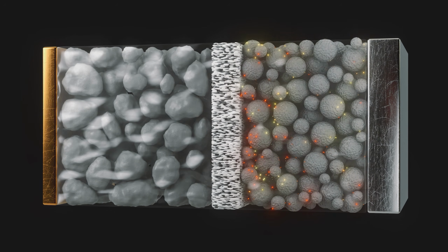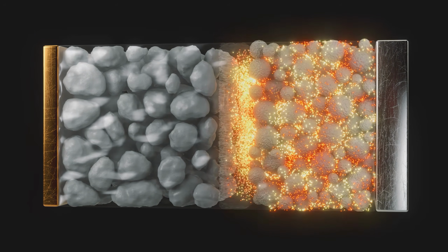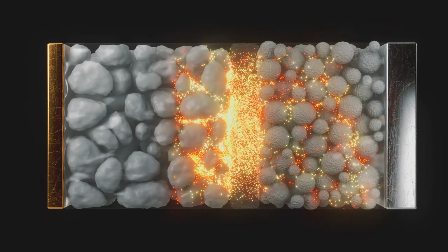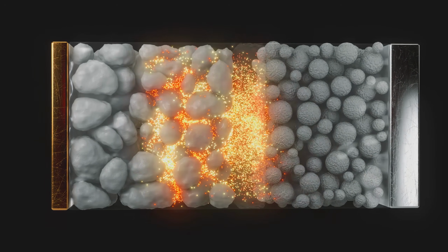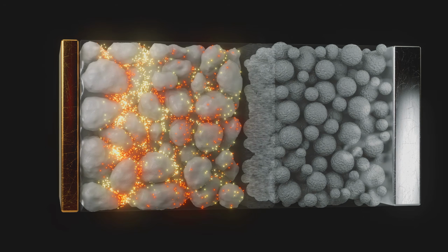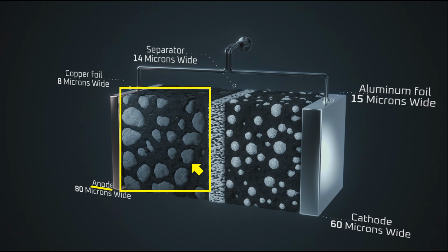Additionally, the lower charge density of the sodium ions also means the electrolyte solution for sodium-ion batteries tends to be less viscous, meaning it flows more easily, which also helps with ionic resistance and charging speeds, especially at low temperatures. The next component to cover is the anode.